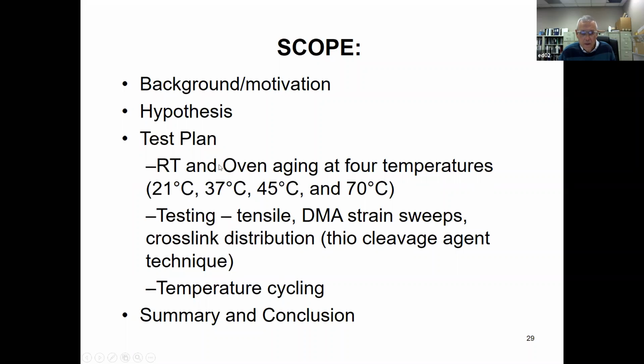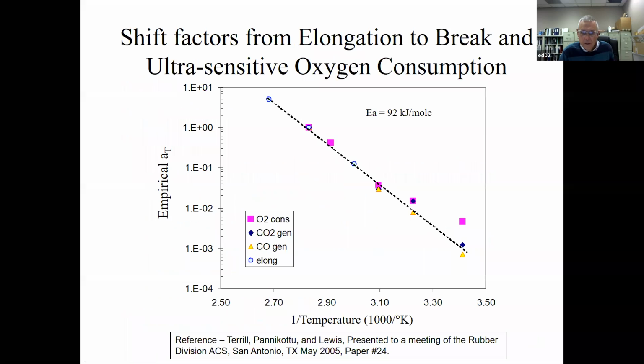So we're going to try to understand the mechanism change, which we think we see around 40 or 50 degrees C. So the next 3 or 4 slides are background or motivation. These are the empirical shift factors from elongation to break and ultrasensitive oxygen consumption, which we talked about last week.